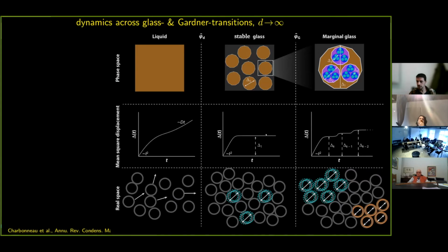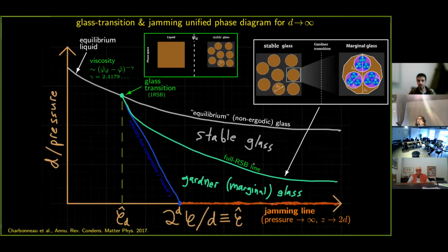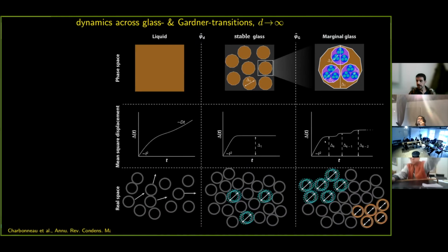and you would never find normal diffusion. Then if you were to continue to compress the system, you would undergo again the Gardner transition, right? You would cross the full replica symmetry breaking line. And in that case, indeed, as John mentioned for the spin glasses, you find the phenomenon that the system doesn't have a well-defined reference state around which the particles fluctuate. They are indeed caged and diffusion is inhibited. Nevertheless, the mean position of these particles is constantly changing because of the frustration and the marginal stability of the state. And that's why if you look at the mean square displacement, you find that it slowly ages in a logarithmic fashion.